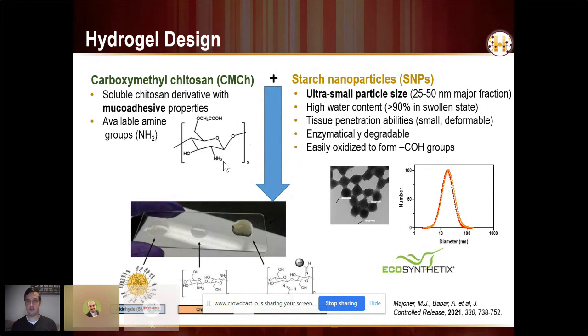They're based on starch, so that's easy, good for regulatory. And we can easily oxidize a few of these repeat units to form aldehyde groups. So if we mix the amine-containing carboxymethylchitosan and the aldehyde-containing starch nanoparticles through Schiff-base interactions, we can get a gel.